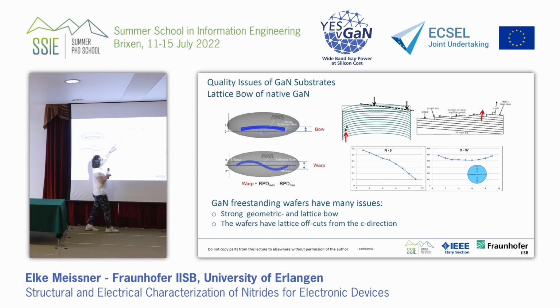And this means that if you cut it in a certain direction, or even if you cut it with no offcut, with zero offcut, you will have steps at the surface. And these lattice planes emerge to the surface in a different, let's say, different inclination angle, and uneven over the whole wafer. So in the middle you have nearly no offcut, and at the sides you have big offcuts. This is all what you don't want in epitaxy, because the epitaxial condition responds to the surface of the wafer.